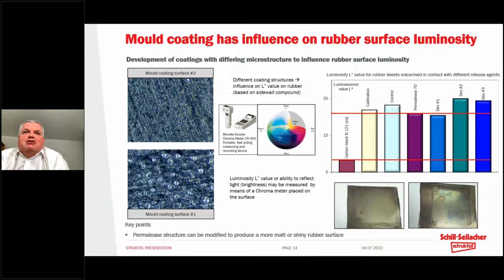And indeed, to some extent, this is really possible to do. We can see here, looking at two different surface coatings, number 2 and number 1. Microscopically, they look very different. Number 2 looks a smoother coating, whereas number 1 has some interruptions. If we measure the L values, we can start to see quite different behavior in L values, and compare that to pure carbon black, which has a very, very matte and non-shiny appearance. And then looking at the bottom right of this image, we can see two rubber sheets that were molded against metal plates with these different coatings applied to the metal plates. So on the left-hand side at the bottom, a very matte rubber sheet where the surface has been a little interrupted and we don't see a surface reflection, compared to at the bottom right. Now we see a much shinier, glossier surface.